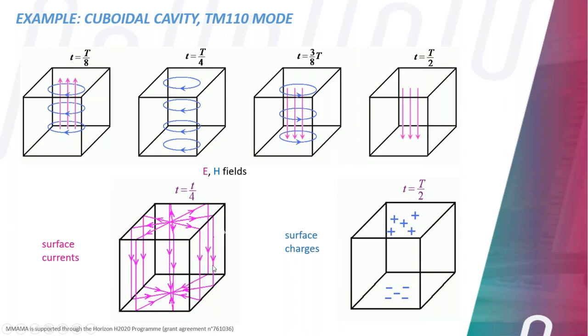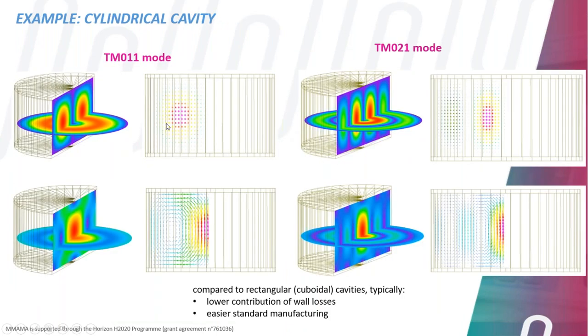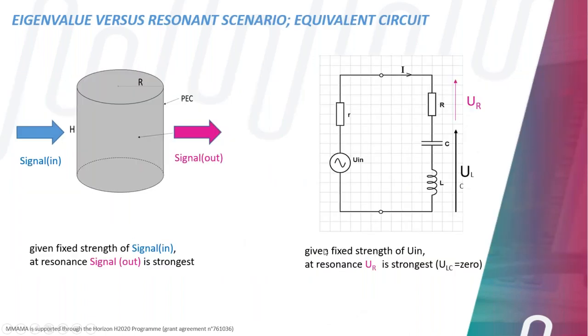The field patterns are associated with currents flowing on cavity walls. And this tells us that when our resonator is not made of perfect metal, because we do not have perfect metals, the sidewalls will contribute to the losses in the cavity. Some solutions now for our cylindrical or circular cavity, some modal field patterns. What is my main observation and why we will be using cylindrical cavities? As you know, the surface area of a cylinder is smaller compared to a surface area of a rectangular cavity. So in general, the contribution of metal losses will be lower, and also these circular cavities are more compatible with standard manufacturing techniques. So that explains why cylindrical resonators are used in material measurements.